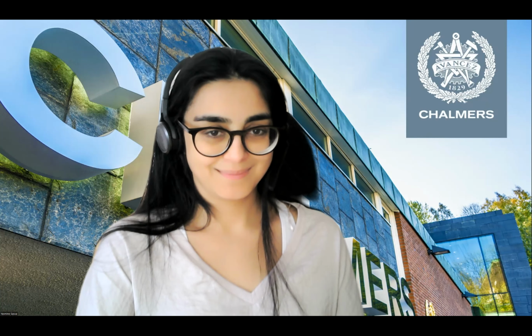I cannot say not at all, but it's true that for the specific case of CeCu2Si2, at least when I was writing my thesis, you had like 6 different papers saying different pairing symmetries. I don't particularly remember the case for the muSR, but you have specific heat measurements saying S+S. You have also another paper claiming that it's D+D, or a mixture between the two, by another STM paper. So yeah, we cannot give a hard answer on what the pairing symmetry could be for CeCu2Si2.